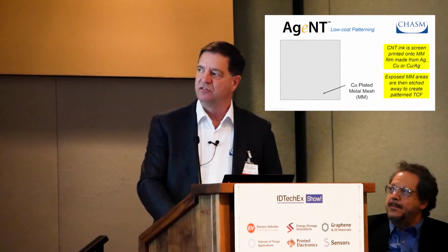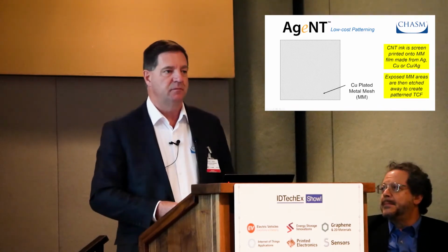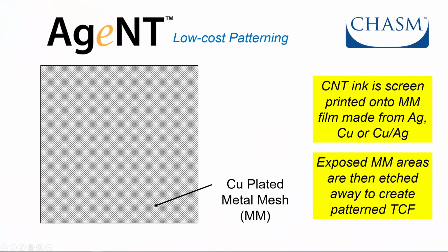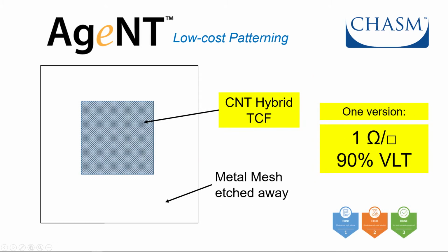The same process flow can be realized with metal mesh film. We start with a metal mesh film. We screen print carbon nanotube ink. The carbon nanotube ink is a multifunctional material. Not only does it make the metal mesh better, it makes it more robust. It makes it perform better, especially in RF applications. But it acts as an etch mask, just like for the silver nanowire film case. The exposed metal mesh is etched away. Print, etch, done. Very affordable, very standard way of making printed circuits, flexible printed circuits.